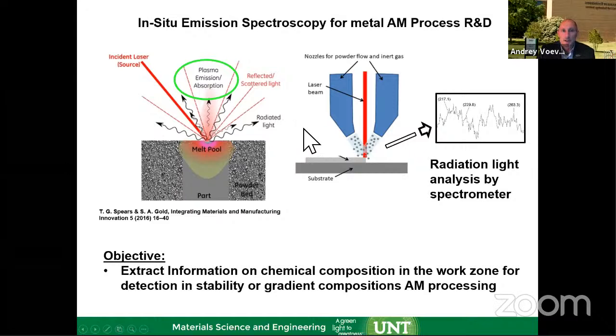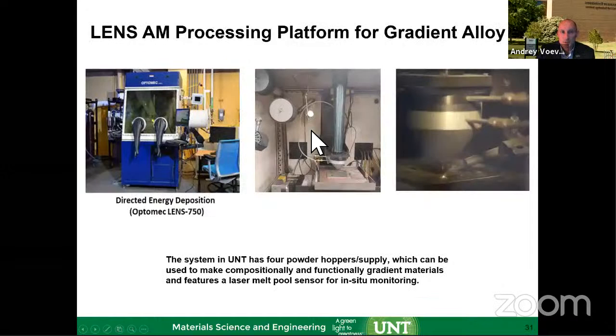Okay, I'm sharing some of the initial results which we have. Before showing the spectroscopy results, I'll show you that we're using the Optomec LENS 750 system. I mentioned we've had it for more than a decade. Dr. Raj Banerjee is working with this, and that system is modified with 4 powder hoppers. So you have 4 nozzles, and you look inside of this chamber, which is inside of the glove box, so it's under a controlled argon environment.